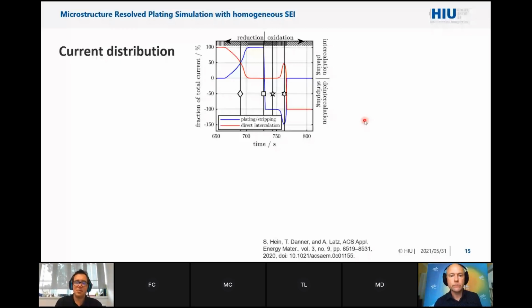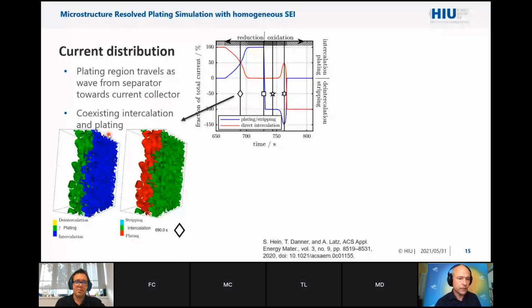Again, here are the simulations for plating, here are the simulations for stripping. The red one is the part that is directly intercalated, and you see that the plating degree is slowly increasing, and at some point you have no intercalation anymore, and you have a full plating regime. So this is exactly here. You have plating at the green part, intercalation at the blue part, or if you now consider the current which is going into the plating, you have no plating in the green one, here just intercalation, and full plating here in the red part. The more interesting one is the stripping situation.